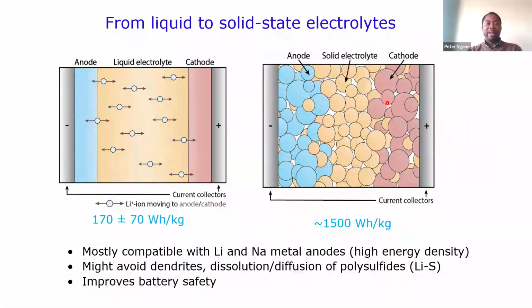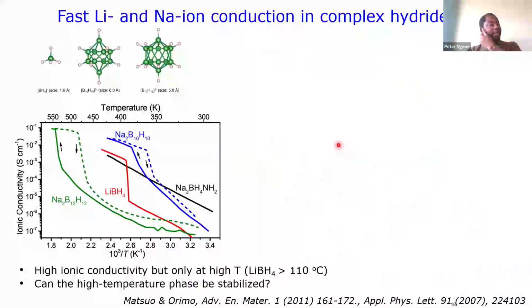But then we have to find a solid material that is conductive. So surprisingly, these complex hydrides, in this case, this is the complex anion, can be bonded to either lithium or sodium or magnesium in any case. All these complex anion hydrides also show high ionic conductivity. So here, we measure the conductivity of this material as a function of the inverse temperature, which means that the temperature is increasing as we go like this, right? So you can recognize these are all hydride-based materials.